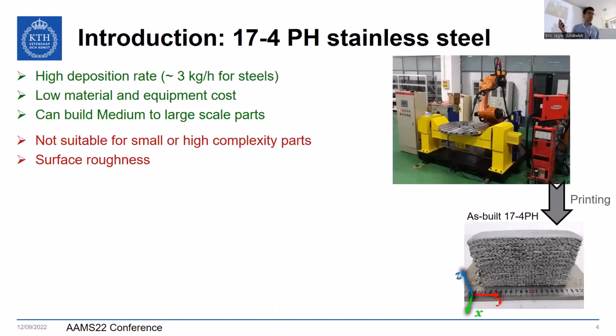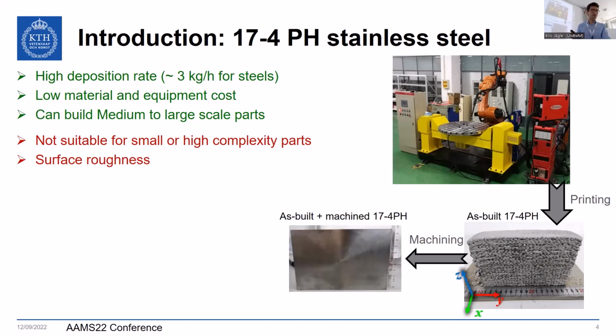Why? Because this process has some interesting advantages. It allows achieving relatively high deposition rates. Costs for materials and equipment are relatively low compared to other processes, and it also allows building medium to large scale parts. However, it's not really suitable for small or very highly complex parts, and the surface roughness is not always so good. Here you can see on this picture that the as-built material has quite a high surface roughness and would need machining for probably most industrial applications.